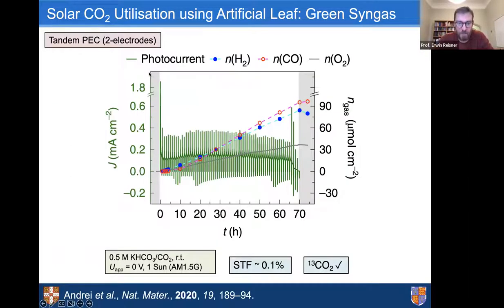Here's some data. This shows now the photocurrent generation over time during irradiation in the white area here. And this is a real standalone device with no applied bias. And you can see the current generation here. It's quite stable for the first couple of hours or even days. And then we see this dramatic collapse. And this collapse is actually when the sealing starts breaking and we get some traces of moisture into our perovskite. It dissolves the perovskite and it really destroys the device.